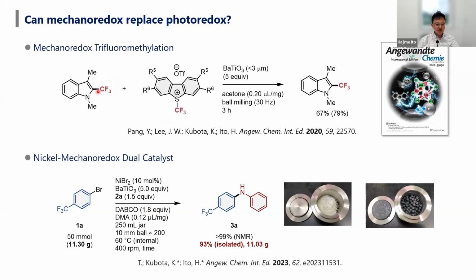Okay, this has a mistake, there's no trifluoromethyl here. So, cross coupling between a bromide and amines - I'll also skip some amine partners. With amine 2A, nickel bromide was of course reduced by barium titanate to promote these reactions.